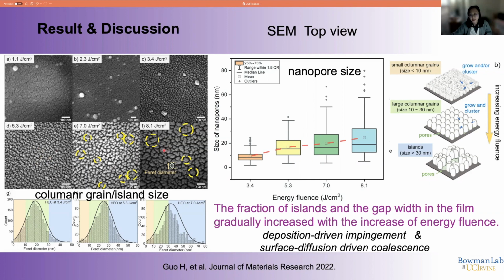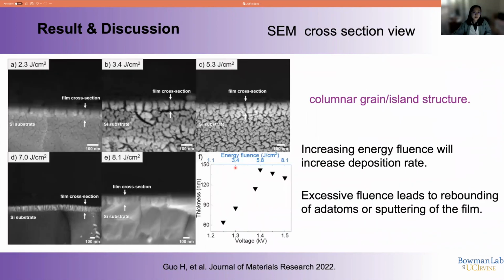larger random island. As you can see in the schematic, at the low energy fluence, they are just very small and thin columnar grains. With the increasing of energy fluence, they tend to grow and cluster. Finally, at very high energy fluence, there are a lot of islands in the films. Also leave very large nanopores inside. But these nanopore islands seem not very uniform in size and arrangement.